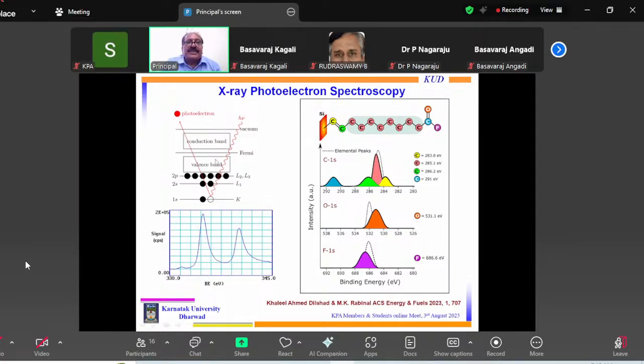What this technique does is that high energy X-rays are sent to the material, and the energy is so high that it will knock out the innermost electrons. Once the electrons are knocked out, they come out as photoelectrons. Then one can measure these electrons and create a spectrum. What you have is a signal of photoelectrons as a function of binding energy. Binding energy is specific to every material. Therefore, by measuring binding energy very accurately, one can find out the chemical composition of a surface. One can measure it with very high precision.